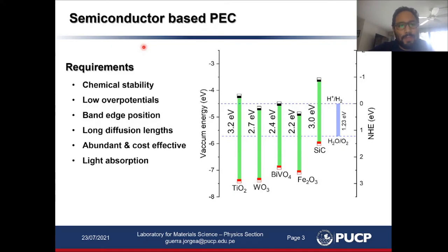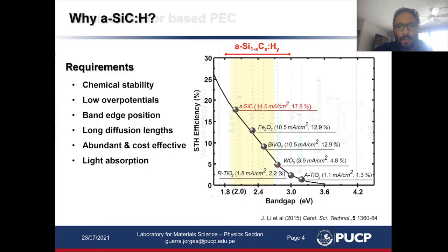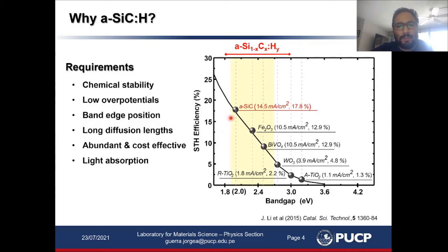In the case of materials used in semiconductor-based photoelectrochemical devices, they should fulfill certain requirements like high chemical stability, low overpotentials, a suitable band edge position to drive the reactions, and the material should be abundant and cost-effective. Also, the bandgap of the material should be high enough to drive the reaction, as well as low enough to have a sufficiently high photocurrent when using sunlight.